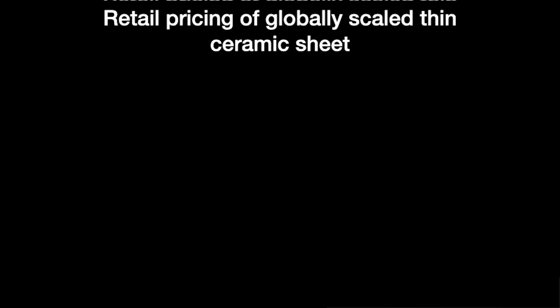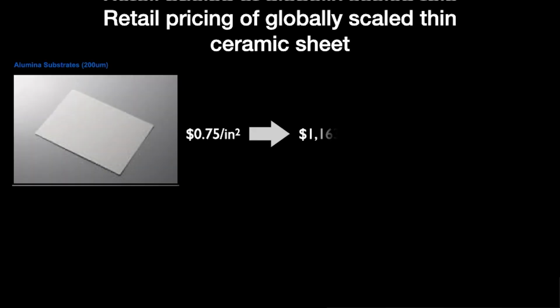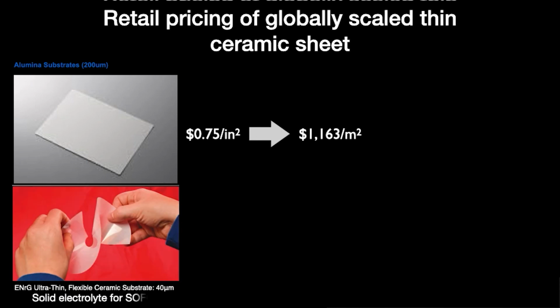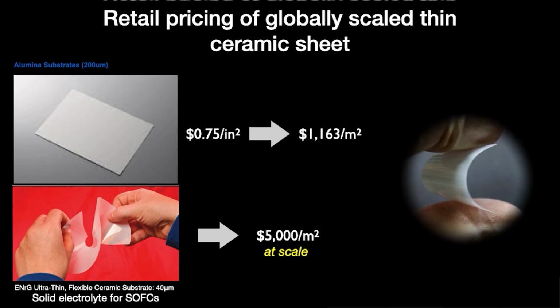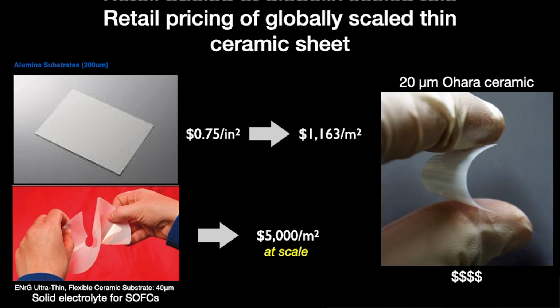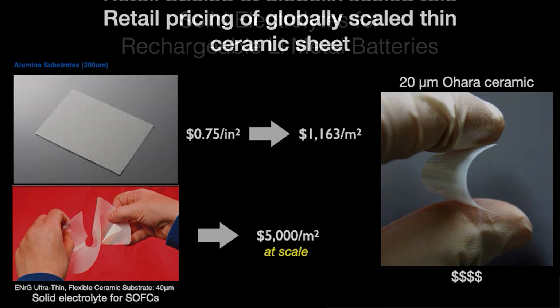If we look at just the retail pricing of ceramics that are already globally scaled, alumina, a pretty common material, easy to make, is about $1,000 a square meter. And here's a material that's at 40 microns. A company named EnrG was producing this material. At scale, they estimated they could get to $5,000 a meter squared. And we work with this LATP material. Here you see a 20 micron membrane. We typically don't work with such thin materials because the seawater batteries don't need them. They're very expensive, and so we don't see this as a path forward just because of the scaling issues and the cost. There are other issues regarding dendrites, but the cost issue is a big one.